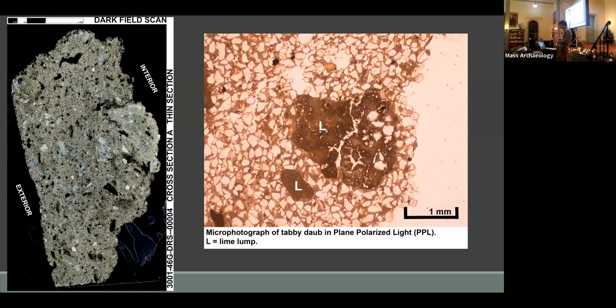And so an excessive presence of charcoal can indicate the use of a lime rick for burning instead of a lime kiln, which would filter out the charcoal and would also result in a more consistent burning process. And also cross sections of charcoal within the thin section can be used to identify what wood they were burning for fuel.